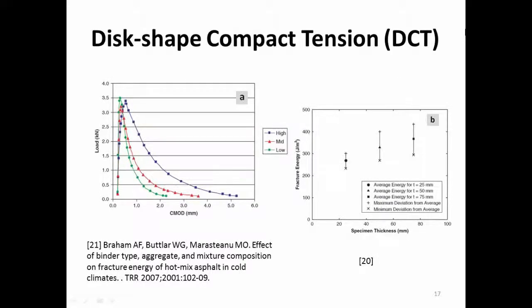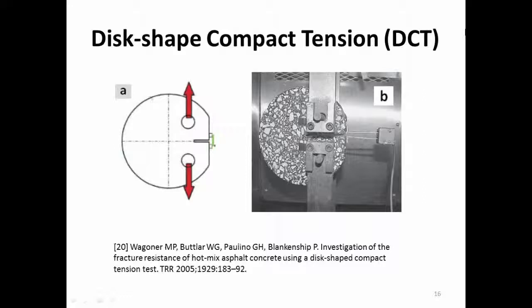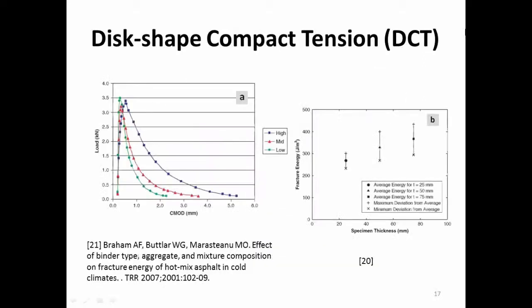So this is a representative disk-shaped tension test curve, and you see the peak load for this test doesn't vary too much at different temperatures, but as the temperature increases, from the green one to the blue one, the area underneath the curve increases. That means the fracture energy increases. But one interesting thing here is, if you look at this specimen closely, you need 2 holes to apply the forces, right? So that means if you vary the thickness of this specimen, this is in 2D and the third dimension is orthogonal to the paper, okay? If you change the thickness of the specimen, the fracture energy you observe is changing. So what's the size effect of this specimen? We don't know.